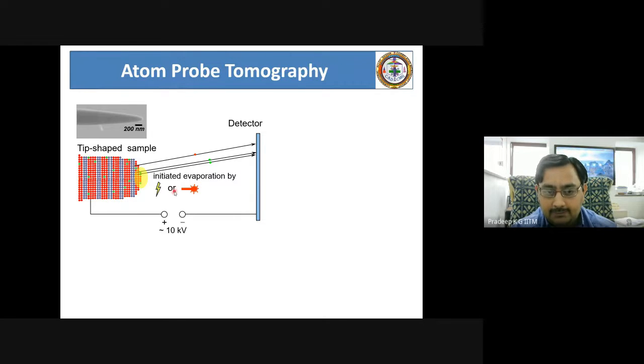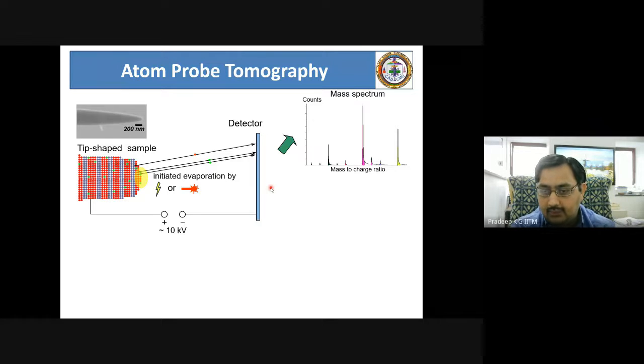The biggest advantage of this technique is that the position of the tip and the position of the detector are well known. That means the distance between these 2 locations is well known. And we all know that each individual atom in the periodic table has its own atomic mass. That means to cover the same distance between the tip and the detector, each atom is going to take a different time. Every atom, based on its atomic mass, is going to use a different time to reach the same distance. And therefore, when you get the time taken by each atom to reach the detector at a fixed distance, you will be in a position to interpret the atomic mass of the species that has been traveling over the distance. And therefore, we get what is called a mass spectrum, where you can independently look at all the isotopes of all the chemical species present in the periodic table with their number of detections as the number of counts. That means you can have different counts coming in, and the chemical species are identified based on their atomic mass, in principle giving rise to time of flight.